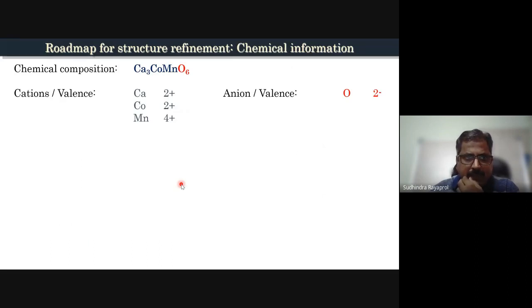The next step would be to provide the input structural information. What is our structural model which we want to refine and fit to our observed data? The chemical composition of my sample, which I have prepared, is Ca3CoMnO6. Because it has ionic bonds with cations and anions, I have to do the balancing. I know calcium 2 plus, cobalt 2 plus, manganese 4 plus, and oxygen is always 2 minus. If I do that, it balances my equation. So this has to be my composition, Ca3CoMnO6.